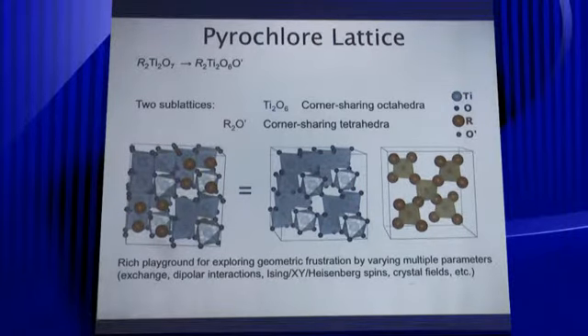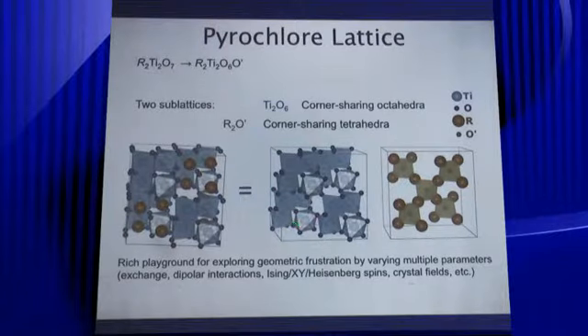When you're looking for new materials, you want to make sure that there's a match between the rare earth site and the B site, if you'd like, right? But we don't want that match to be too perfect, or else you'll have site disorder. So it's a bit of a chemistry game trying to match different sites that are close in size scale, but really not too close together.